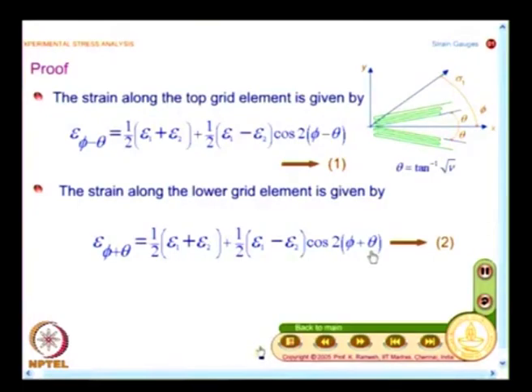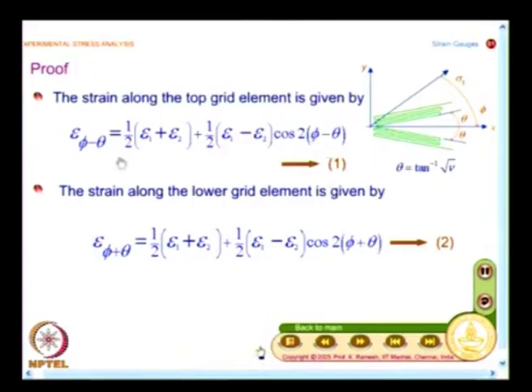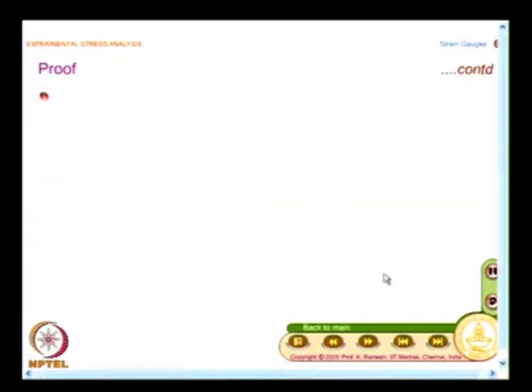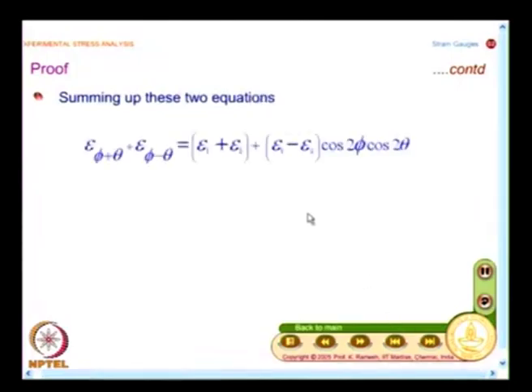See, in strain gauge instrumentation, we design complicated gauges, but finally we will also raise a question, can I do the stress measurement with a single conventional strain gauge? If you look at the theoretical development, I have cleverly taken, to start with, the principal stress axis as a reference, and you note one more aspect. Suppose I have phi equal to 0, the expressions for epsilon phi minus theta and epsilon phi plus theta will be exactly the same. You keep this result in your mind, we will use this result when I go and develop whether a single element strain gauge could be used to measure stress. So, we will develop a complicated gauge pattern to start with. In an unknown situation you will do this, but you will also find out whether you could use a simple normal strain gauge for stress measurement.